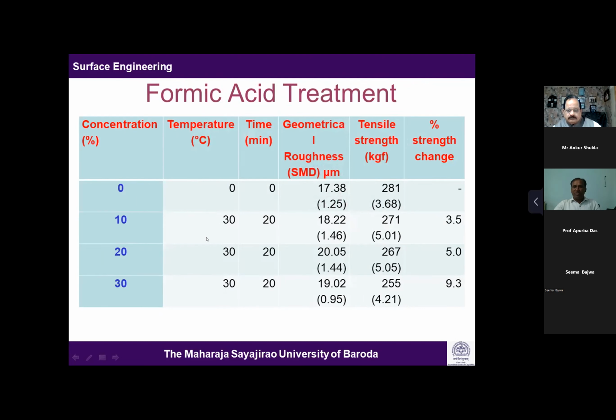So we wanted to see how the nylon responds to different concentrations, temperatures and times of the formic acid. We have taken lower concentration, temperature and time effects, so we hoped for a strength change. The tensile strength is the representation of the bulk properties of the material. We have measured the surface roughness using the Kawabata system.